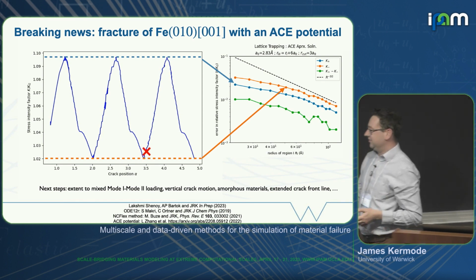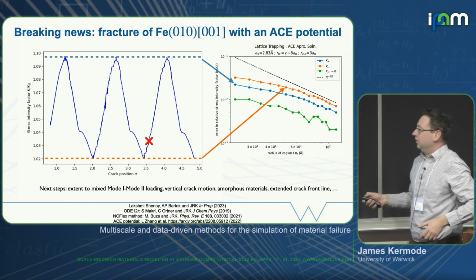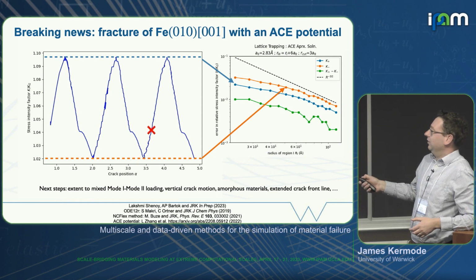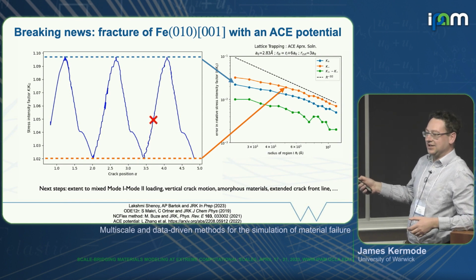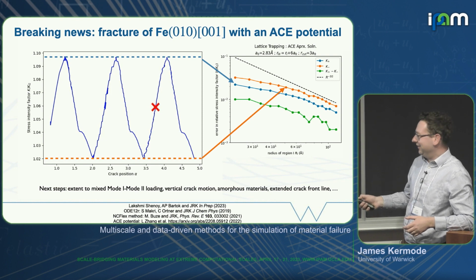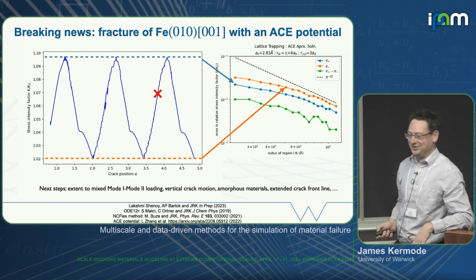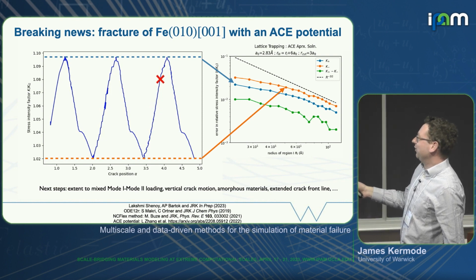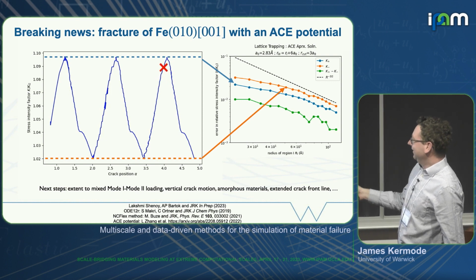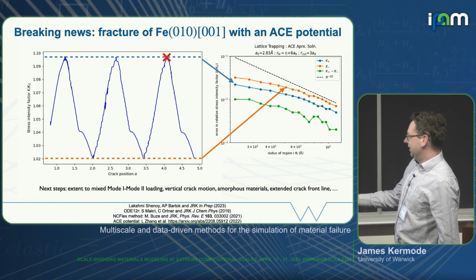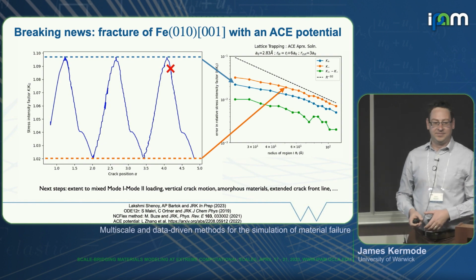We can make the atomistic region bigger and bigger, and we can look at how our estimates for the range of stability change. Is somebody laughing at the jiggly thing going backwards and forwards a little bit? Yeah. So we can look at the upper and lower limits of lattice trapping, and we can see that they actually converge quite well as we go up to 100 or so angstroms.